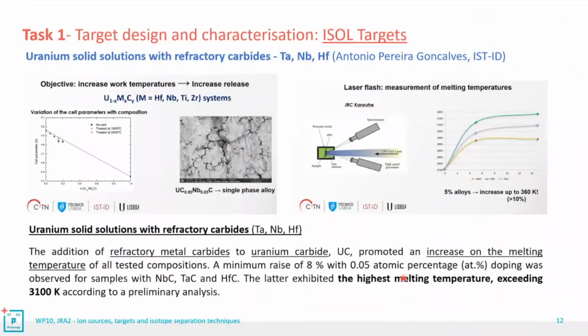regarding ISO targets, this is the important contribution given by ISTID. They worked a lot on uranium solid solutions with refractory carbides, and in practice with these alloys, they were capable of obtaining materials that can work at extremely high temperature, close to 3000 Kelvin. As you know, this is a very important aspect, since high temperature is extremely important for the diffusion and effusion processes that are typical in ISO targetry.